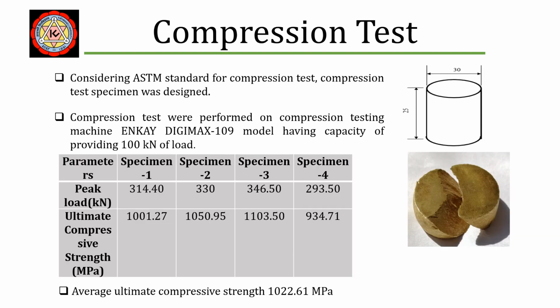Similarly, compression tests were performed by considering the ASTM standard. Compressive tests were performed on a compression testing machine having the capacity of providing 100 kilonewton of load. There were 4 specimens of investment casting to perform the compression test. The average compressive strength was found to be 1022.61 megapascal.